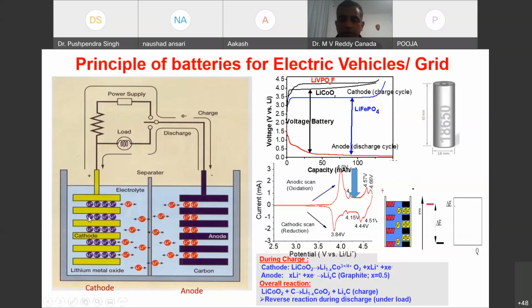So the right side is the current versus voltage potentials. For example, in lithium cobalt oxide, you remove lithium from the structure, and cobalt becomes 3 to 4 plus, with charges to balance. This is called oxidation and reduction. It is a characteristic of any material that you have to get a positive and negative current. That is very useful for what they call the rechargeability.